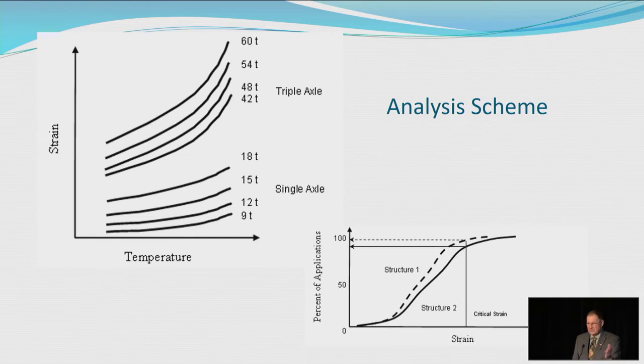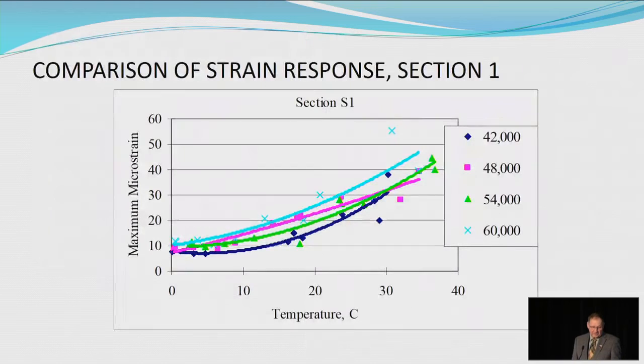And you would do this at different times of the year, and you would come up with different temperatures. And then on the lower right-hand side, you can see a strain distribution for that pavement. So this is what those curves ended up looking like. Because of the fit of the data and everything else, they're not quite as nice as the conceptual lines that you saw on the previous slide.